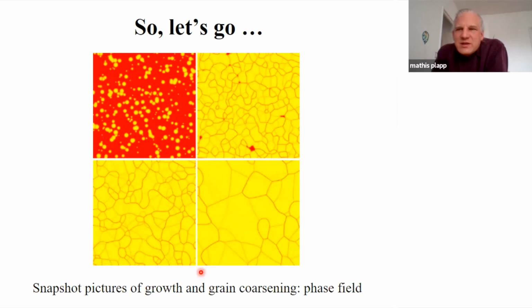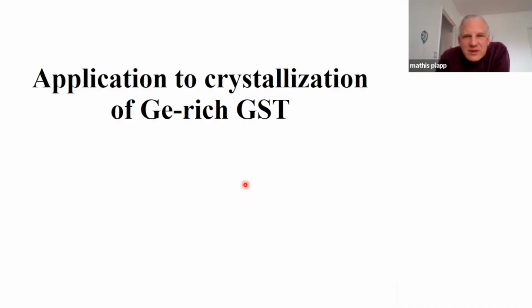So here is a simulation of grain coarsening with an orientation field model. What you see here is the phase field. The first picture is a lot of different nuclei with different orientations that all grow and impinge, and then in the other pictures, you see the grain boundary network evolving with time. You see some grain boundaries more pronounced than others. Those are the high angle grain boundaries, because in high angle grain boundaries, the dip in order is more pronounced than in low angle boundaries.